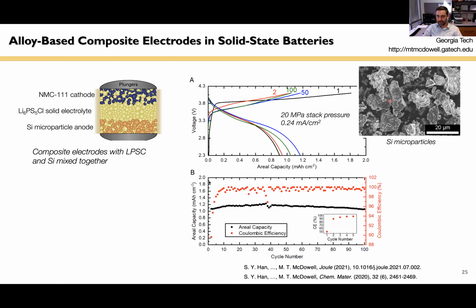And so this is the anode. And we cycle this as shown here. And the results, the capacity retention, is shown below. So the areal capacity is a little low in this particular configuration, but what we're seeing is very good capacity retention over 100 cycles here. And this is with just standard non-treated, non-nanostructured silicon microparticles as the anode.